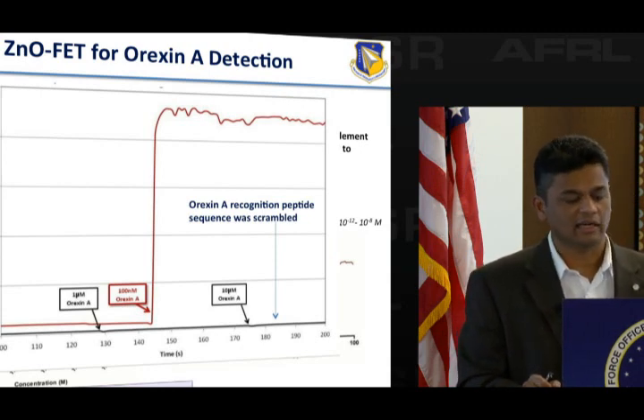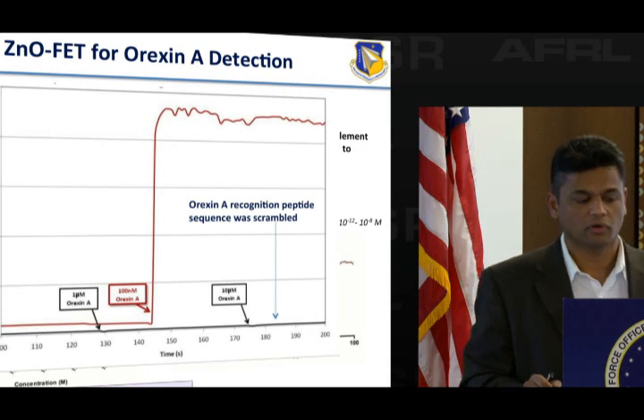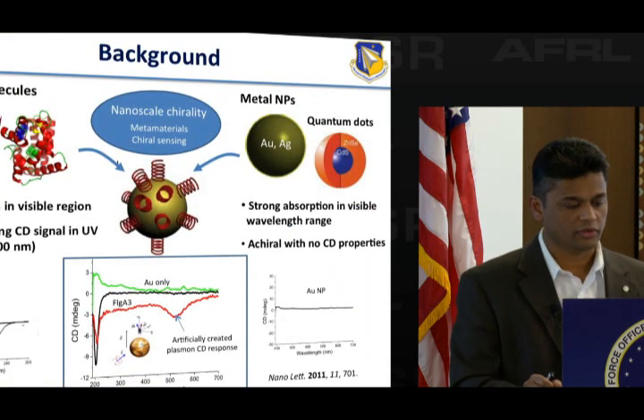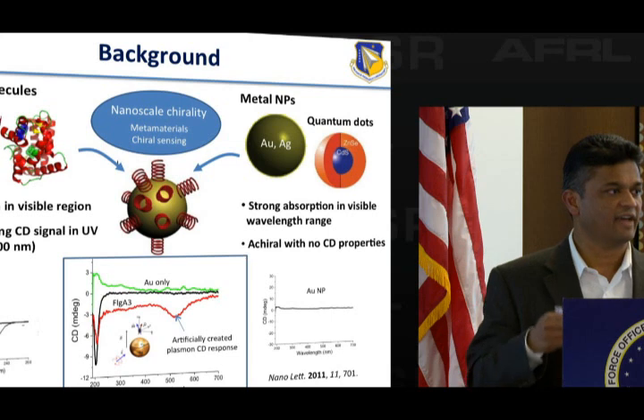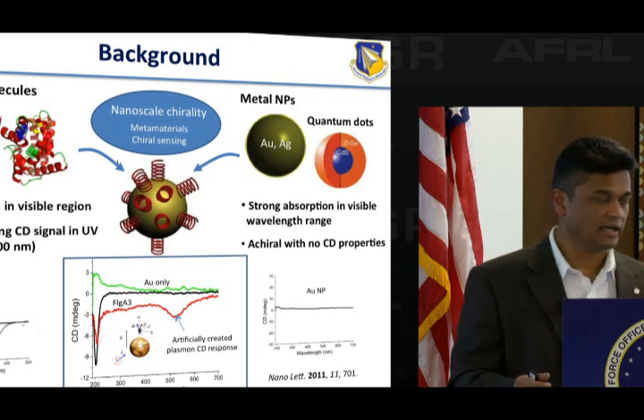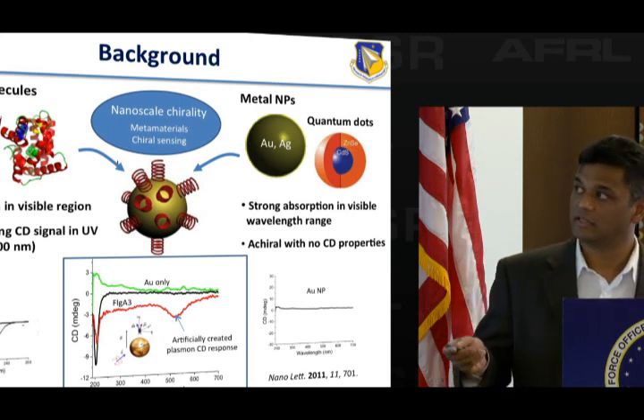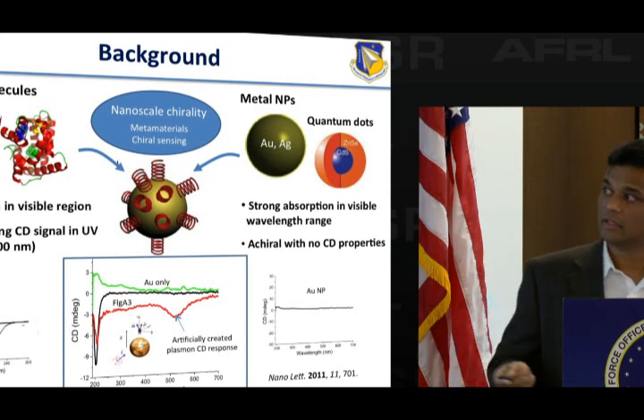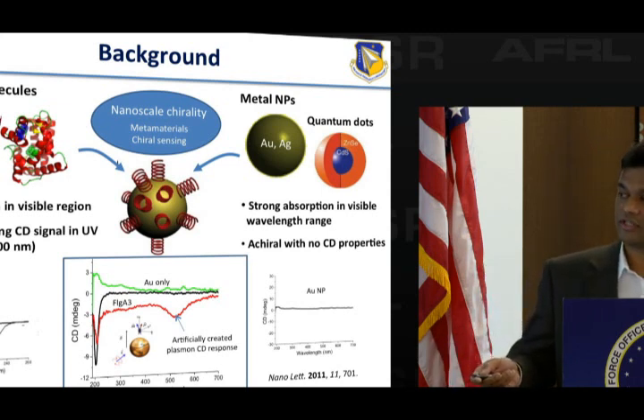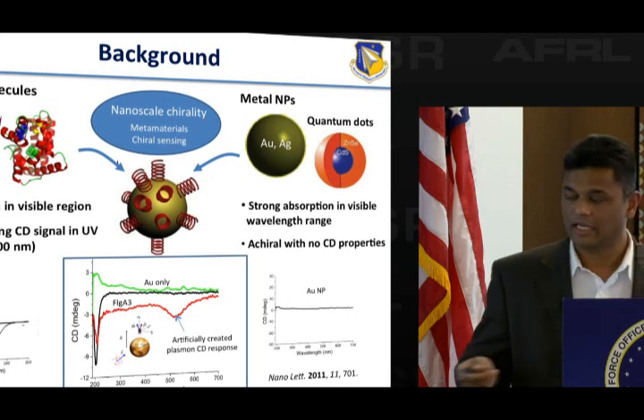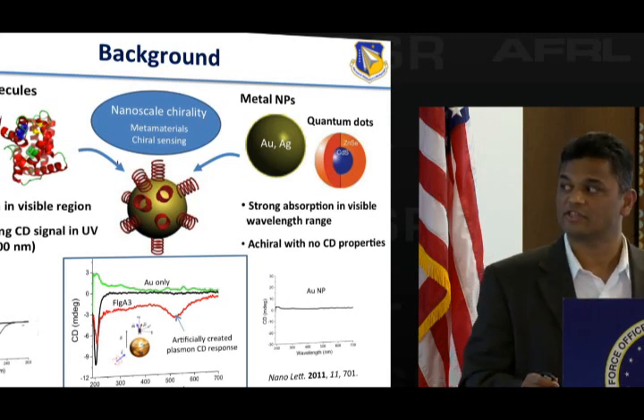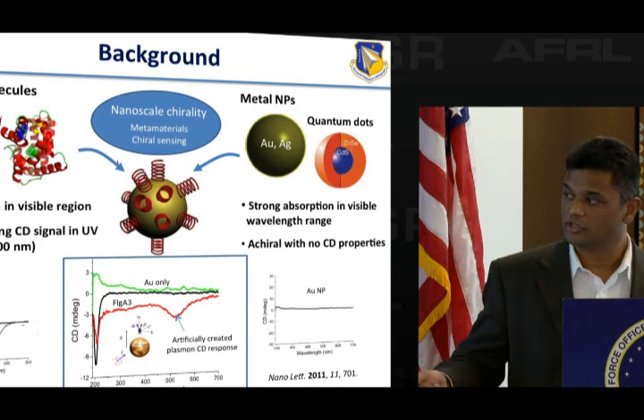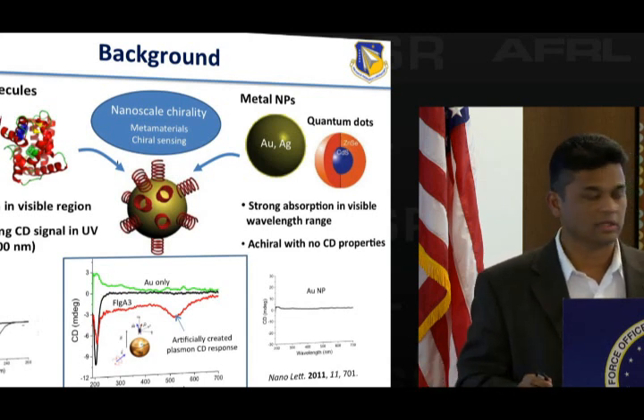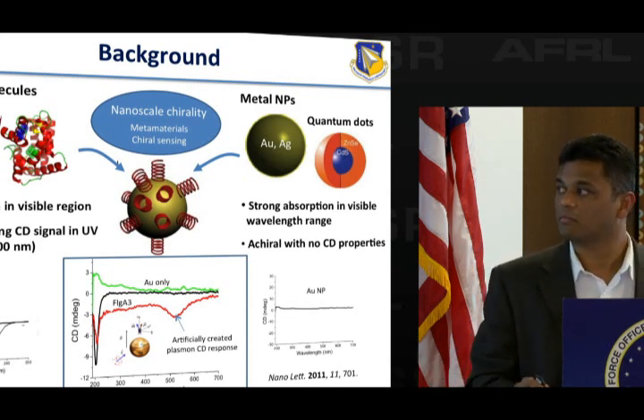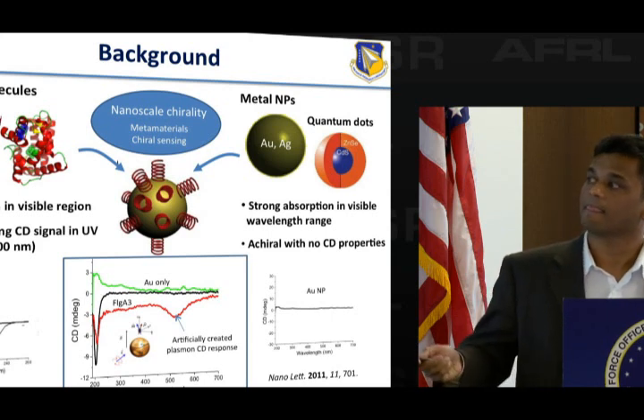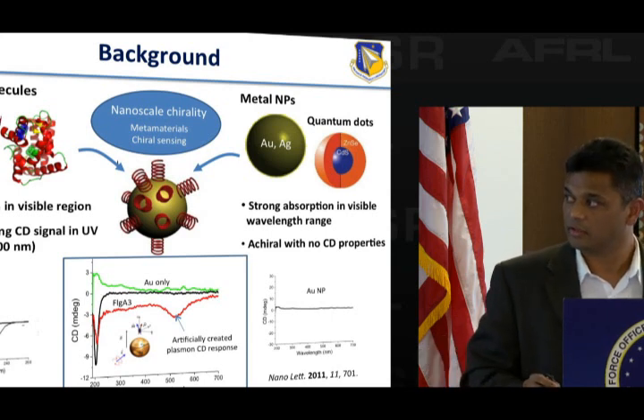Now here's an interesting thing that we've recently begun to notice. When I start putting biological molecules, which are chiral in nature because they have a handedness to them, either right-handed or left-handed, proteins and DNA different, DNA right-handed, proteins left-handed, they have a very nice CD signal. So when you do circular dichroism, in the case of peptides, they have negative ellipticity, so you'd always see a nice dip because they differentially absorb the circularly polarized light, and they absorb in the range of 200 to 300 nanometers.